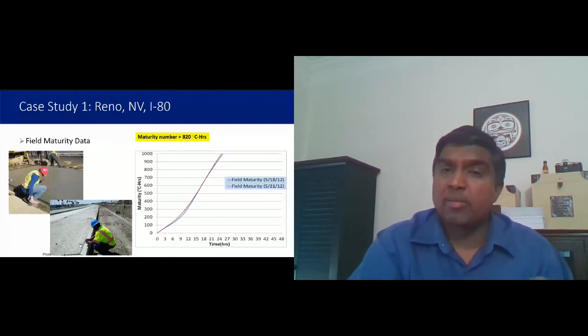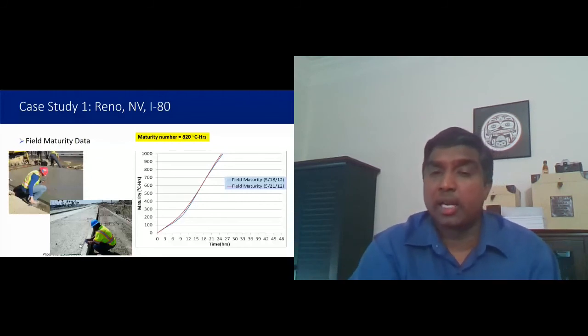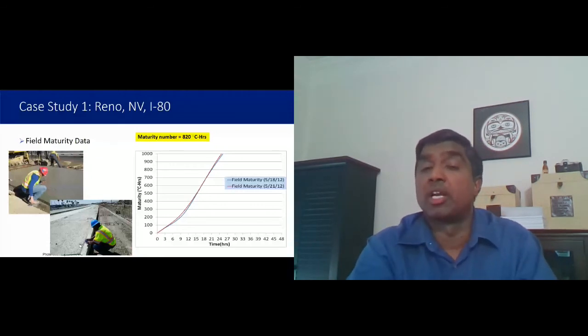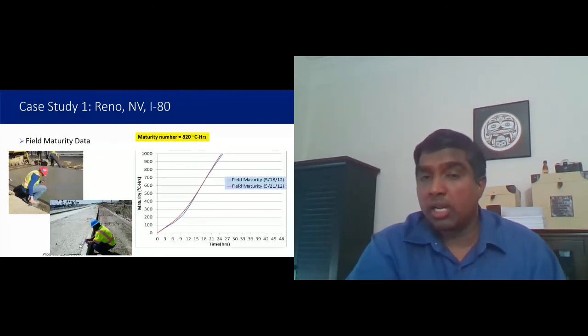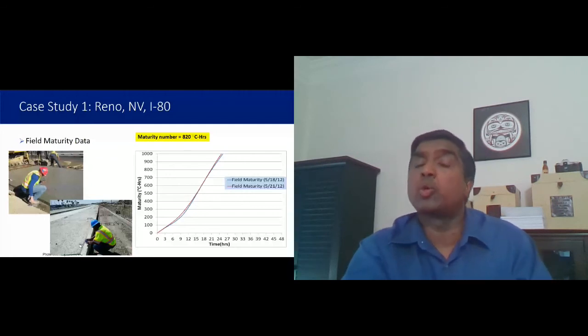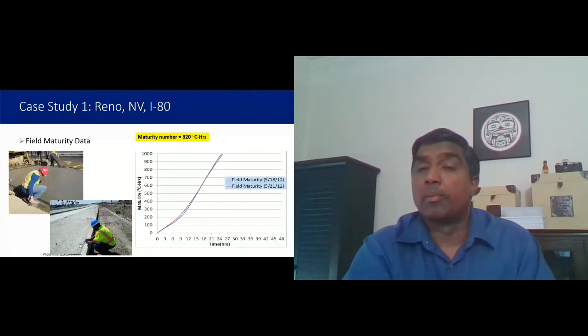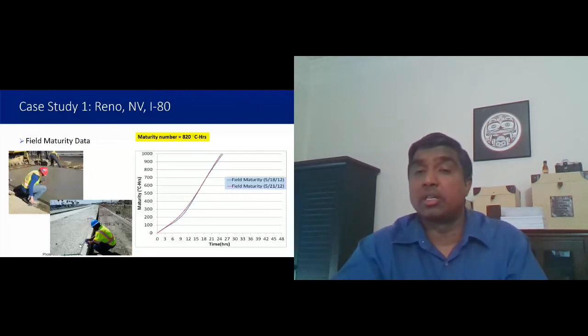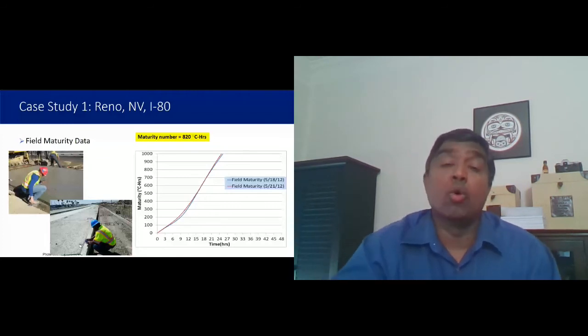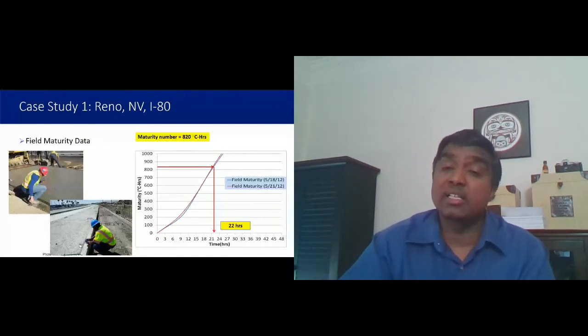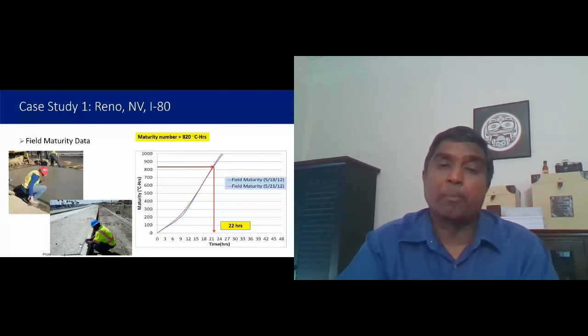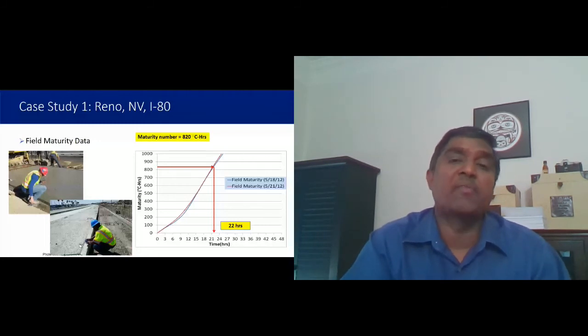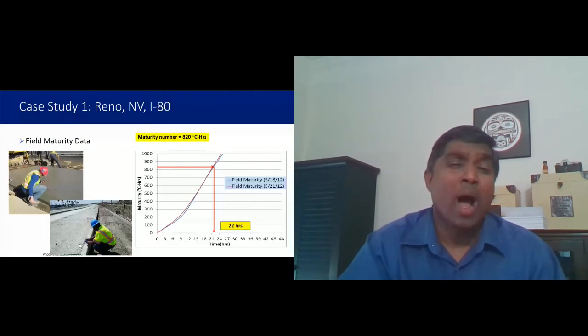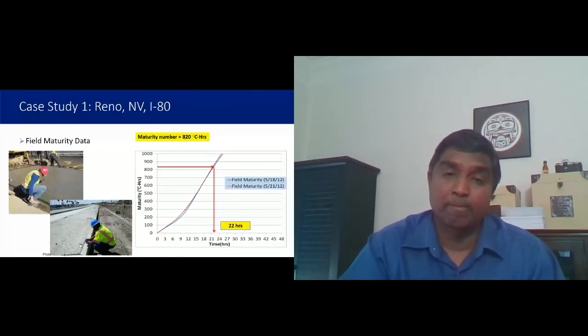Now, if you remember the maturity number we got from the previous slide, it was 820 degrees C hours, right? So we looked at this data and we then found that for 820 degrees C hours, the corresponding time to reach that number out in the field is only 22 hours. So what that means is by the time it's 22 hours for this particular mix, the pavement has reached 550 PSI flexural strength. 1 day. Can you believe that? Just 1 day.